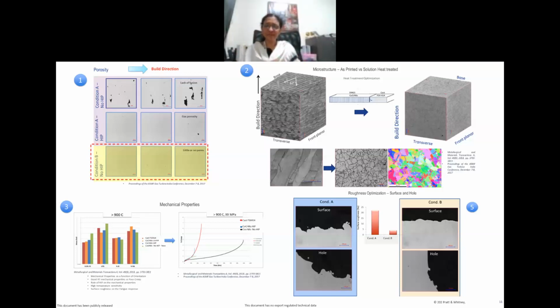Now, if you remember, conventionally, until 10 or 15 years ago, even today, when we do one weld joint, ASME has several sections. ASME Section 9 has so many protocols in terms of what to do, because any weld joint is going to have a tensile stress across the boundary, typically because of the nature of melting near the boundary and shrinkage after that. So we need to do a stress relieving. What I'm trying to point out in the second challenge here can be a boon and a bane, but it needs to be watched out. That means we can use the rapid solidification of additive manufacturing. It's actually a panacea for all the people in metallurgy there.